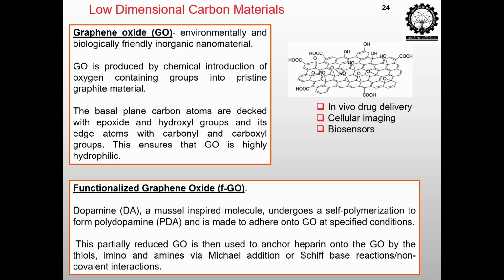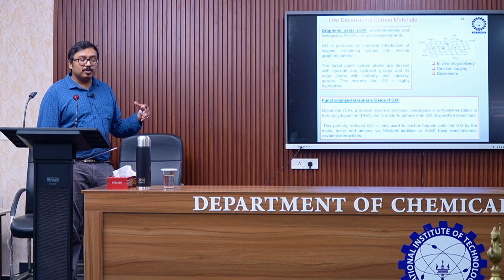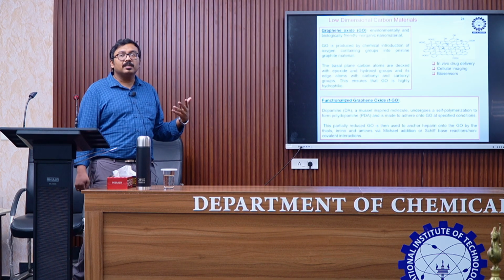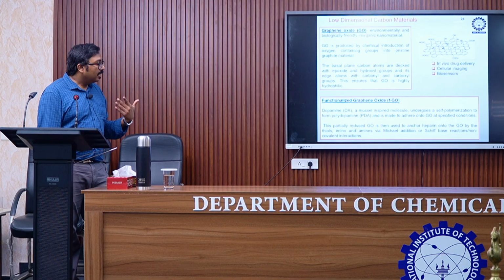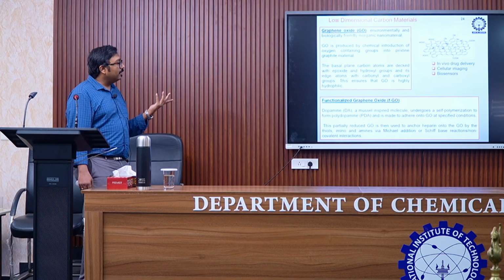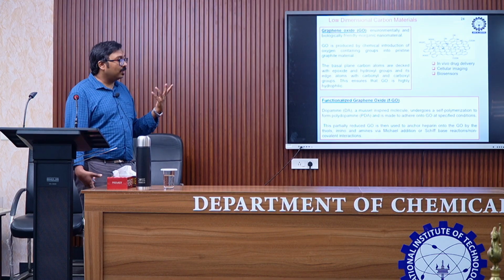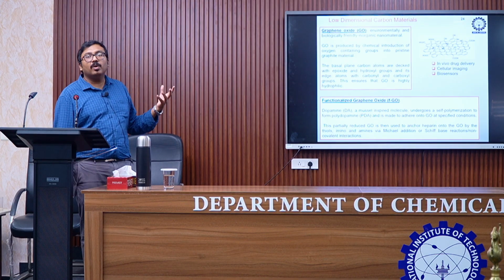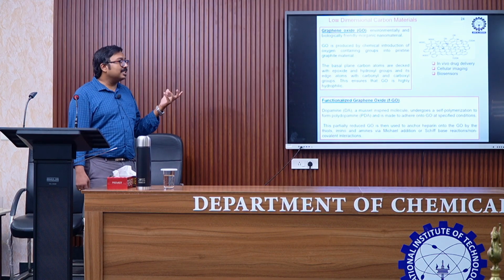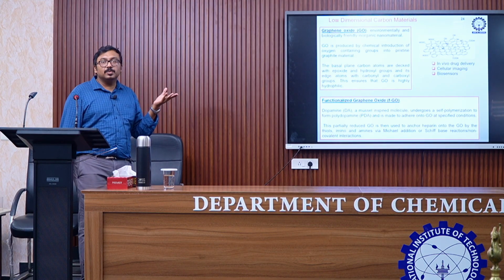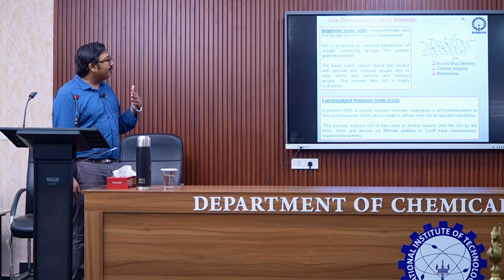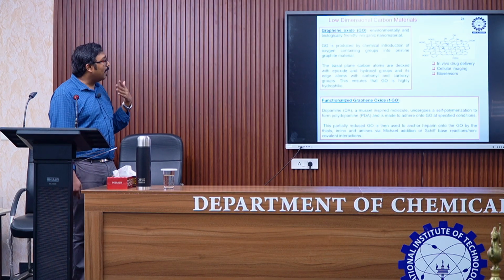So what we have tried to do is improve its performance, its biocompatibility and hydrophilicity, by using different nanomaterials. We have chosen low dimensional carbon nanomaterials, because carbon as such is quite inert and it doesn't cause any toxicity. There have been studies where graphene oxide has been injected into rats and they did not cause toxicity. And anyway, we do not want any of these nanomaterials leaching out from the membrane into the bloodstream as well. So we have done graphene oxide, carbon nanotubes, and